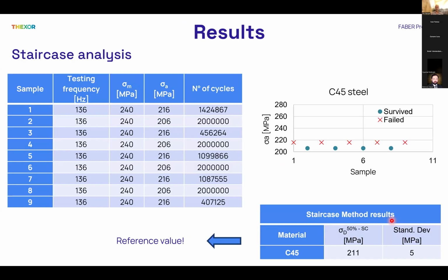The results in terms of fatigue limit using the staircase methodology are reported in this slide. The table on the left side reports the testing conditions adopted during the experimental campaign, and on the right side, the graph regarding the trend between the survived and failed specimens is reported. The fatigue limit estimated using the staircase methodology was around 210 megapascal. This was our reference value in order to compare the results obtained from the classical thermographic approach and the thermographic approach improved using the artificial neural network technique.